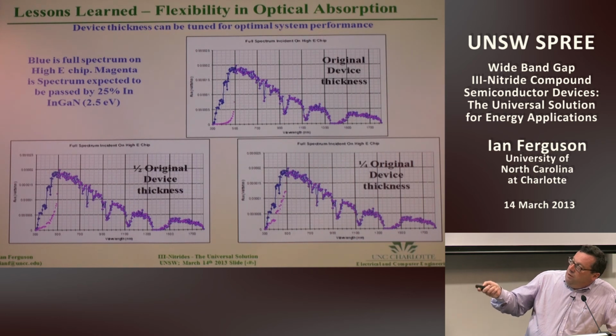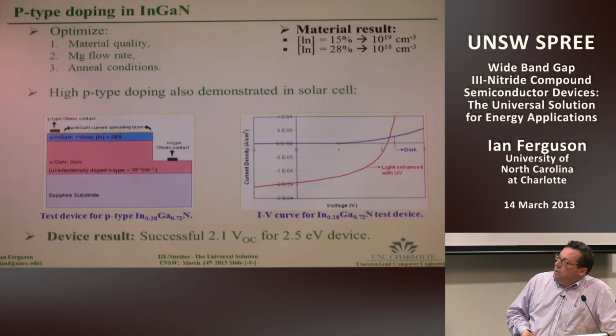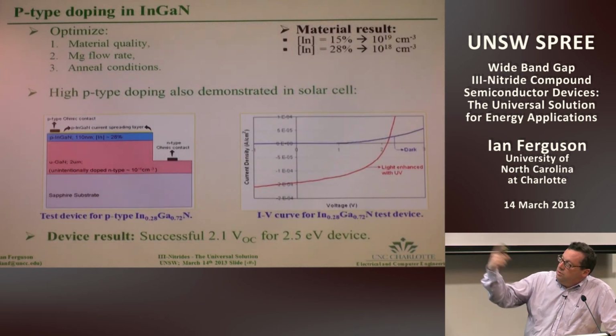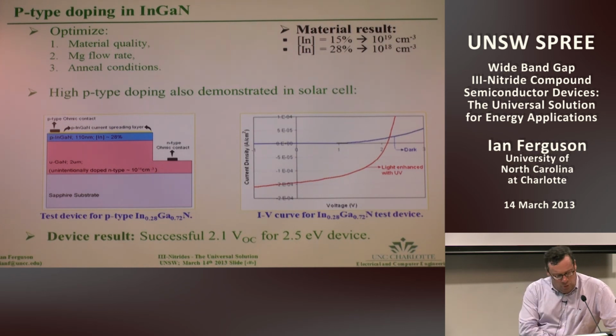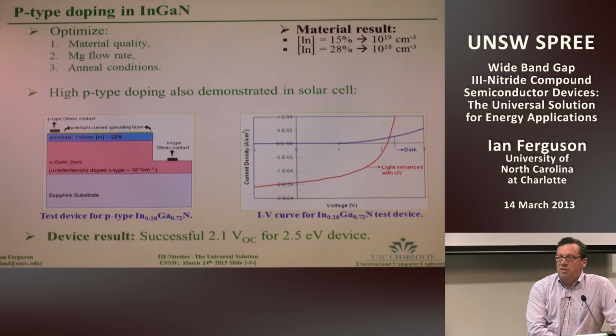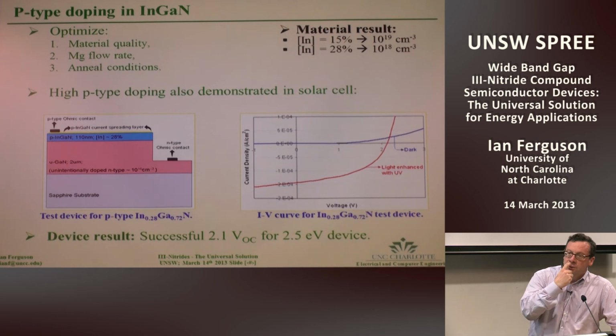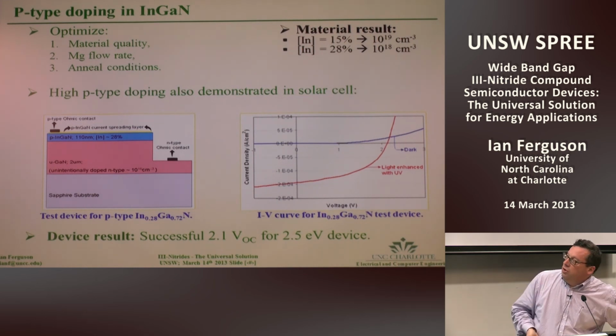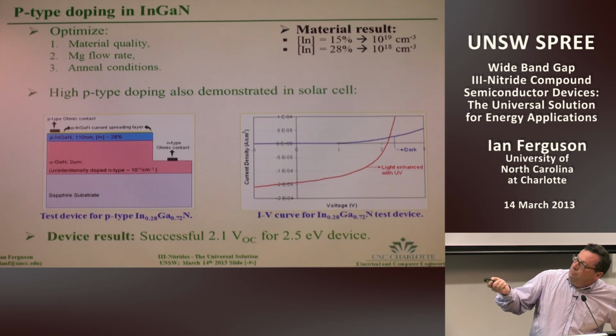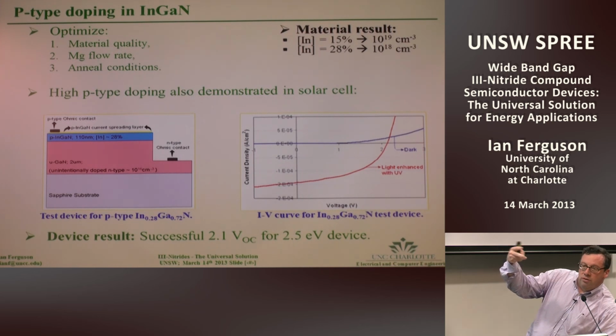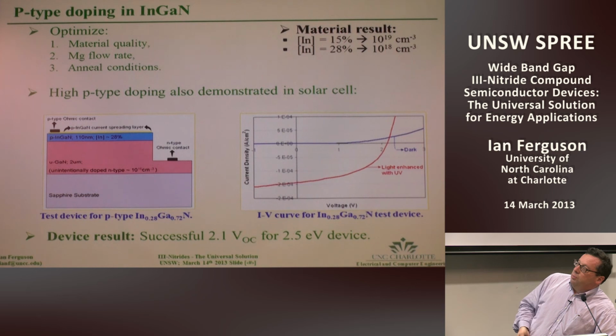Originally we weren't absorbing enough in the red. So we did make devices, and sorry, these were cells. We went through about three or four different generations of cell. Gen is not a good name to use here because of the other connotations with silicon and solar as a whole, but we went through different iterations of devices, and we were doing some devices at the front end to optimize the p-type doping. Here we were trying to dope the InGaN, which again was also problematic. Indium tends to getter oxygen within the layers, so it becomes harder to dope again.